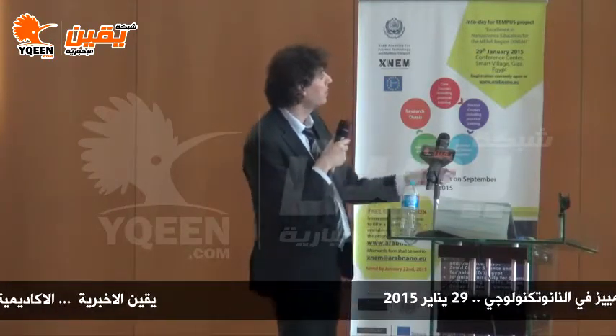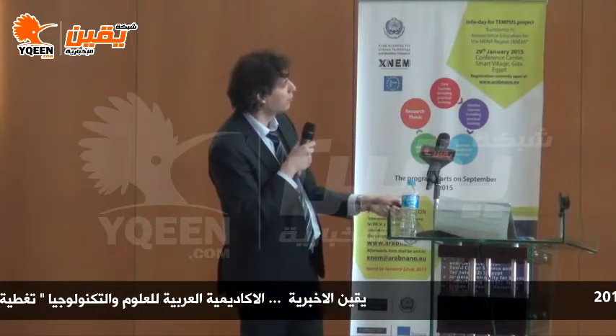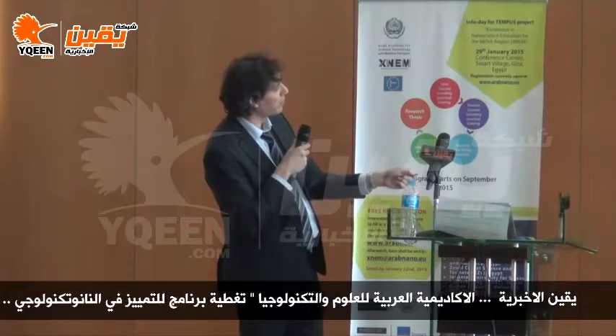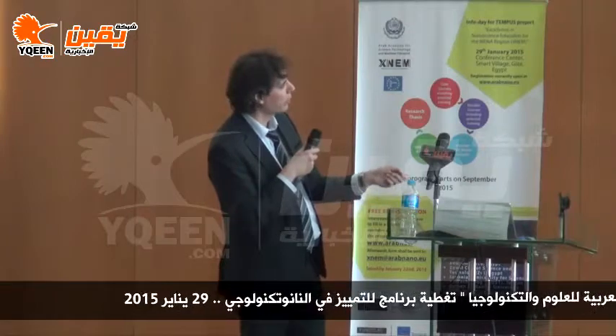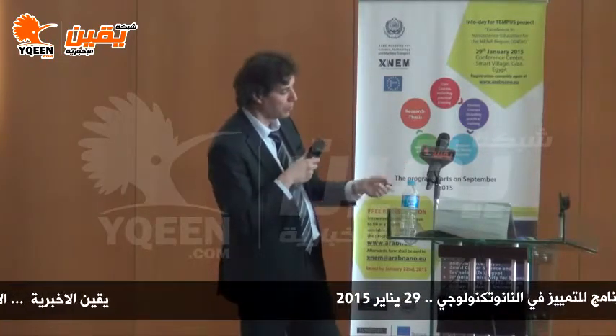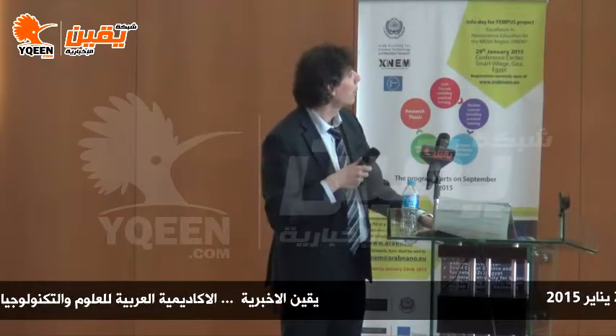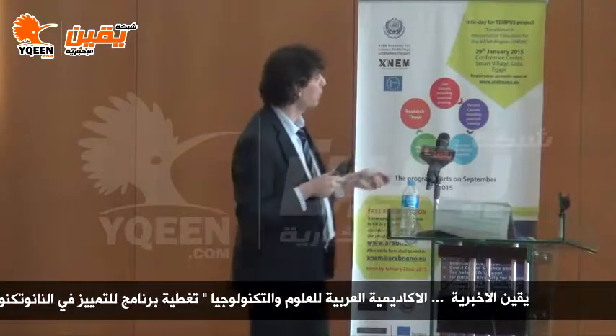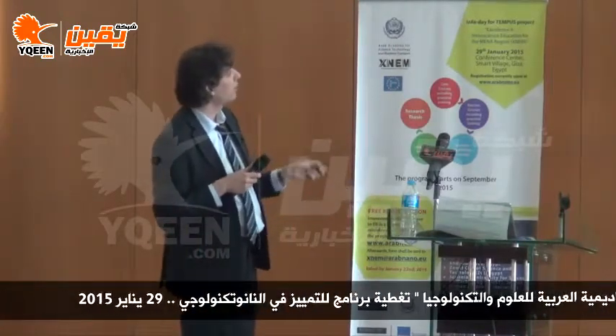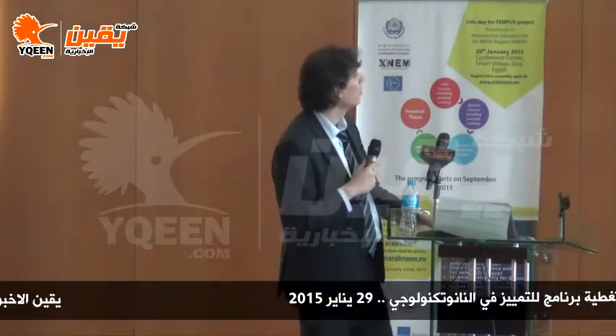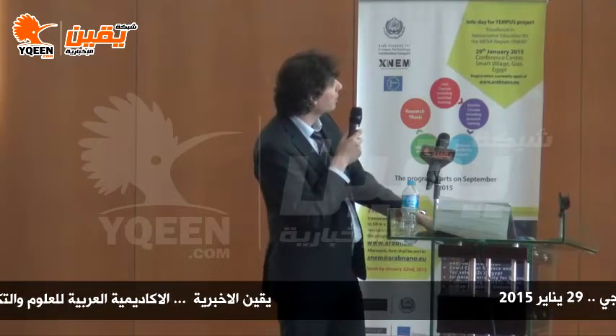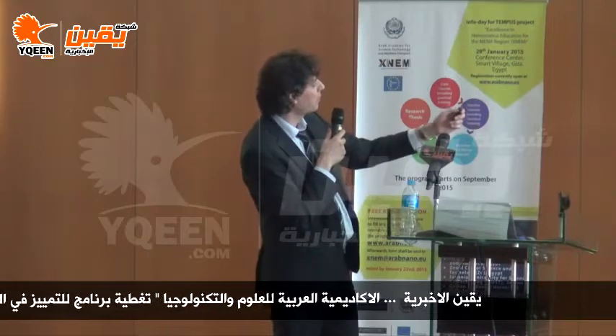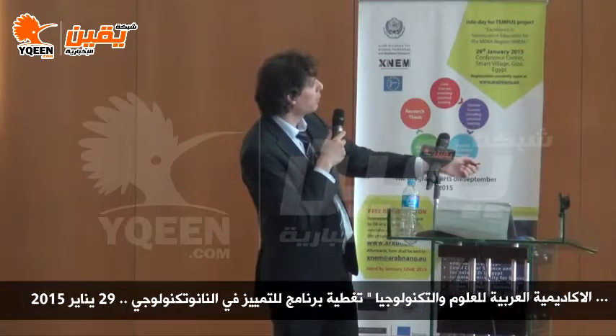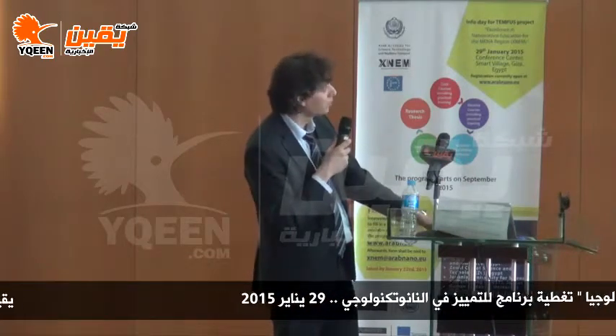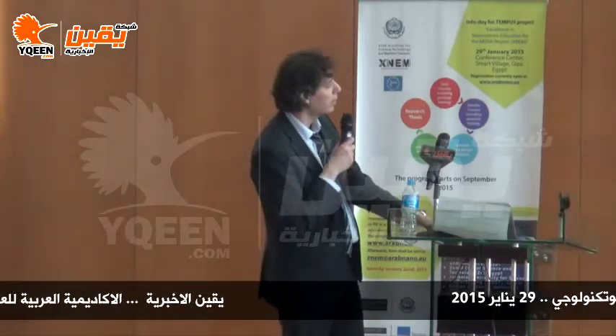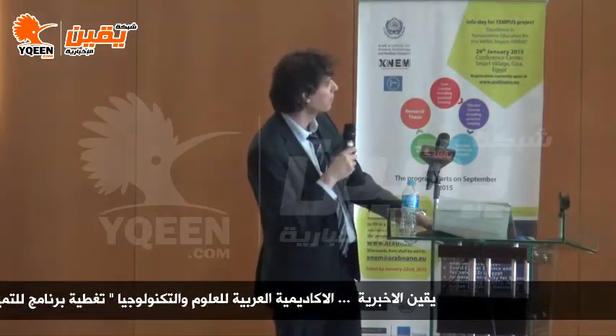Now, some characterization here. If you look at the dark current versus ozone treatment time, and also the photocurrent, we can see that beyond 85 minutes of ozone exposure, we end up with a discrimination ratio between photocurrent and dark current of up to 10 to the 6, which is very good. Now, we look at the spectral response. Spectral response means we shine various wavelengths, and we look at the photocurrent measured. Again, for the various processing times, you can see that the discrimination ratio, the responsivity in other words, is up to 10 to the 8 once we reach 85 minutes of ozone. So surface treatment in such a case is extremely important. The nice thing also with this process is the stability. That was very stable with time.